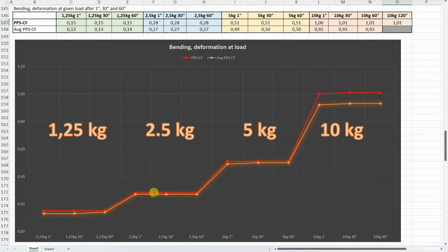We can see very similar deformation compared to the average PPS, except here under 10 kilograms. But what was important for me, just for curiosity, I extended that test under 10 kilograms with 1 minute, and basically you can see absolutely no changes during that additional 1 minute.